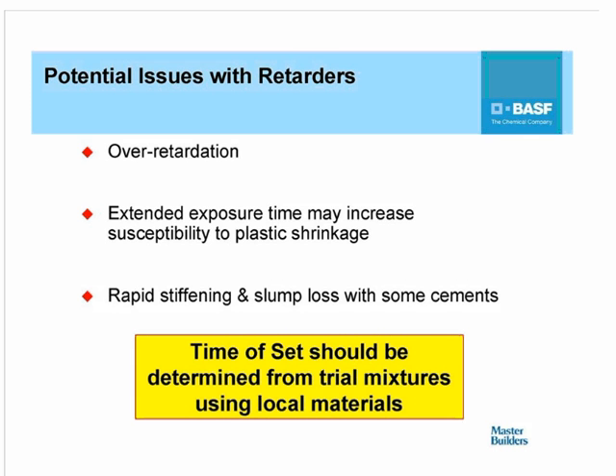With respect to potential issues with retarders, the potential for over-retardation exists if there's an overdose of admixture or depending on the other constituent materials that go into the mix. In addition, extended exposure time may increase the susceptibility of flatwork to plastic shrinkage. But one of the more common problems that sometimes occurs is rapid stiffening when a retarder is used, and slump loss associated with that, depending on the cement chemistry and the type of material that is being used. So even though retarders are supposed to extend the time of setting, sometimes with some cements, you could have the exact opposite happening, where you end up with rapid stiffening.